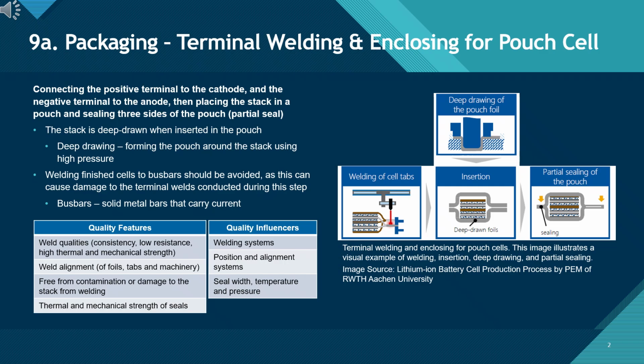Finally, it's important to avoid welding fully assembled cells directly to bus bars, as this can damage the terminal welds formed during this process. The images here show the sequence of tab welding, insertion, deep drawing, and partial sealing.